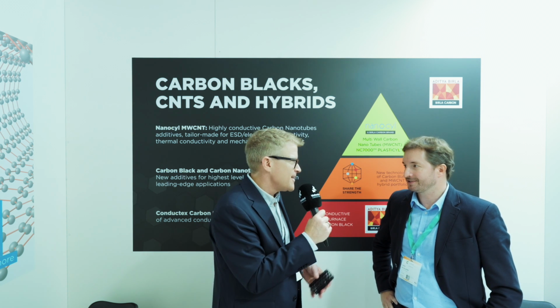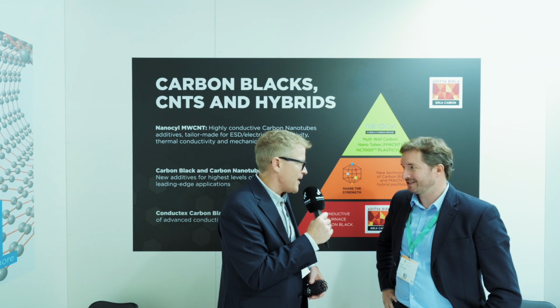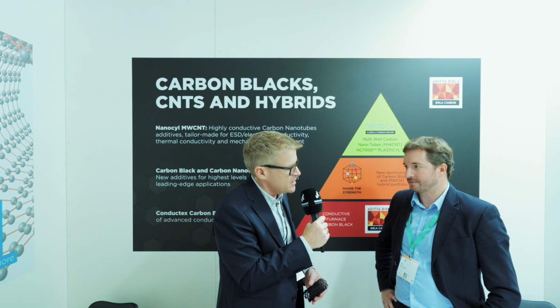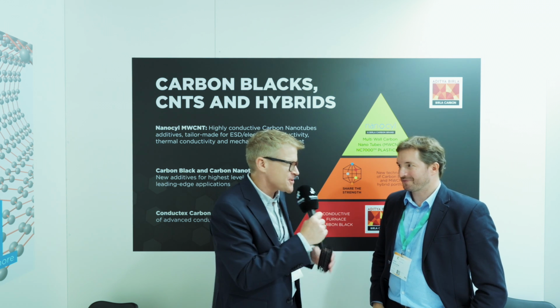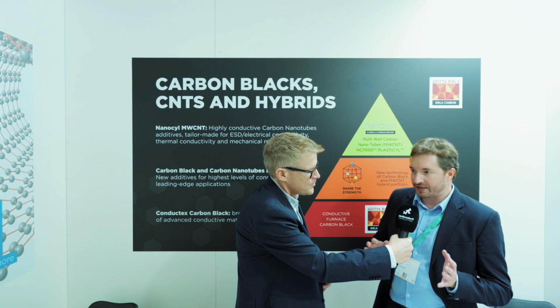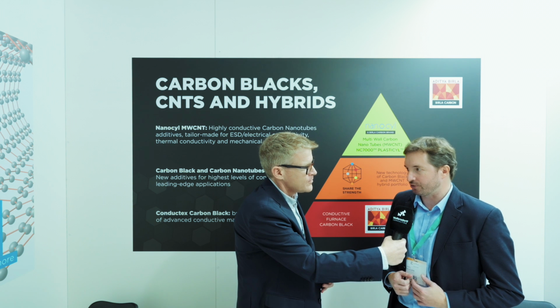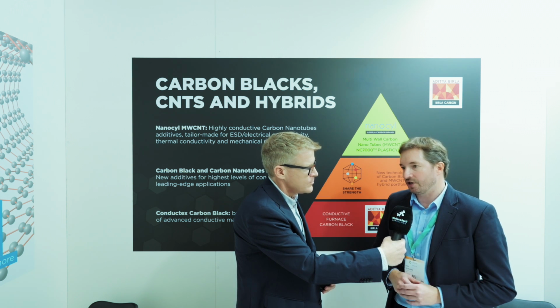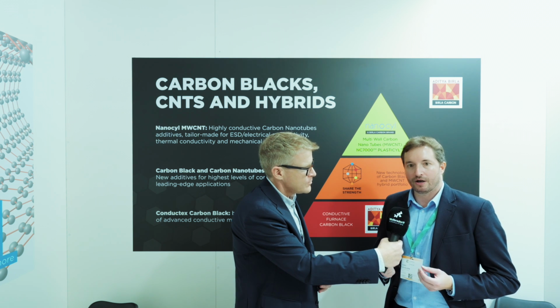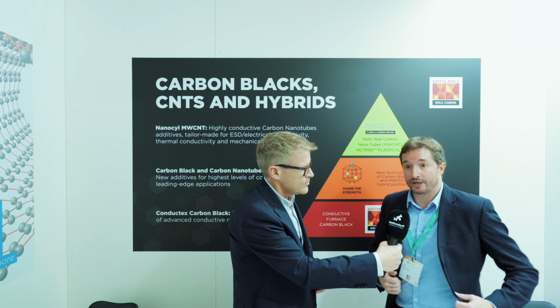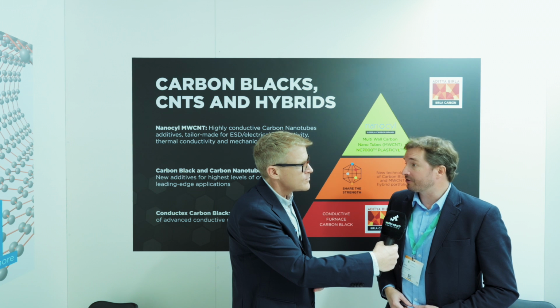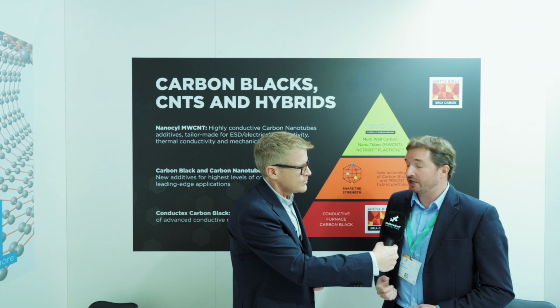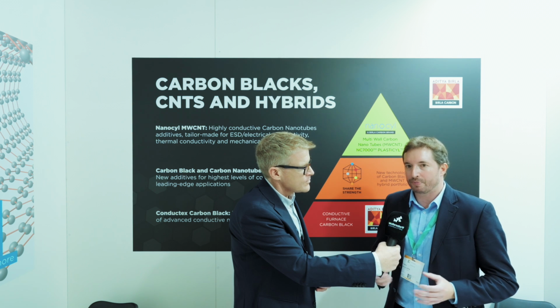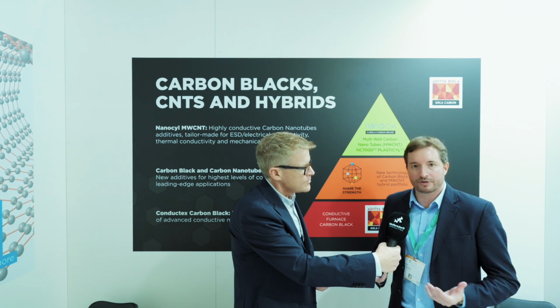Just out of curiosity, a standard carbon black masterbatch, maybe with a Raven carbon black, is up to 50%, maybe 55% is the ceiling. What kind of loading do you have in a multi-wall carbon nanotube masterbatch or pre-dispersion? So we are typically speaking about loading between 10 and 20 to 25% of carbon nanotube. It is with this range of loading that we get the best dispersion of the material, and that we are also able to preserve the properties of the base resin. When you have too high a loading, you start to have high shear force that can damage the resin and lose some properties. So typically, I would say between 10 and 20 weight percent of carbon nanotube is a sweet spot for the optimum properties.